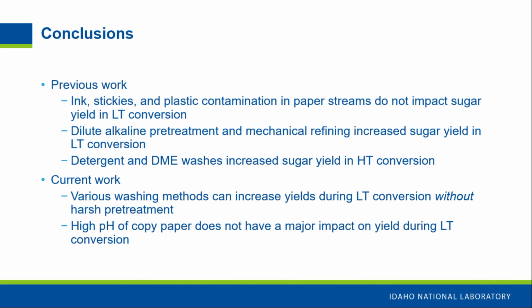In pretreatment you usually have a chemical, and then heat, and then time incubation. In these experiments it was just one of those, just an acid wash. So we were able to get good yields without that heat input and without a long incubation time. And then another interesting thing, obviously, is that the high pH of copy paper does not seem to have a major impact on yield during low temperature conversion.